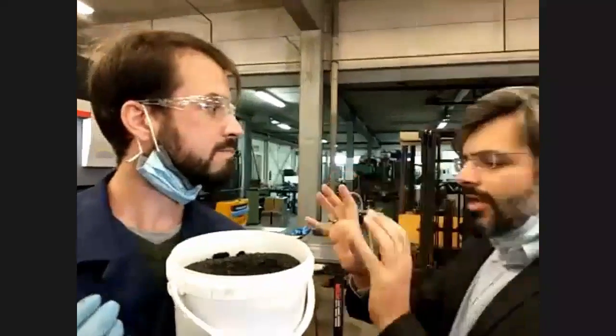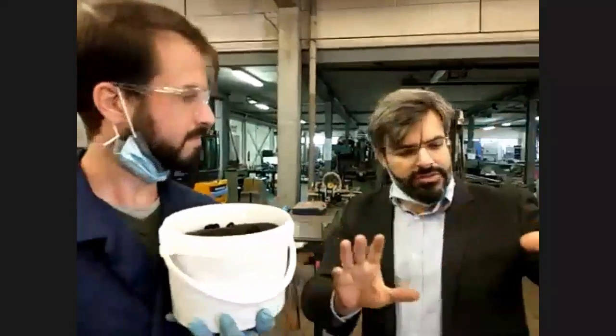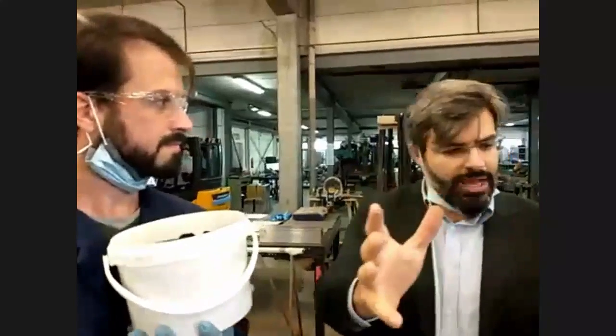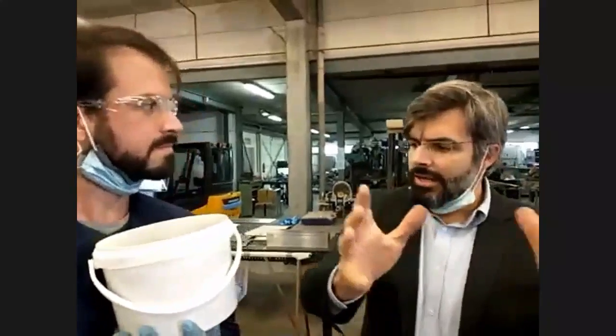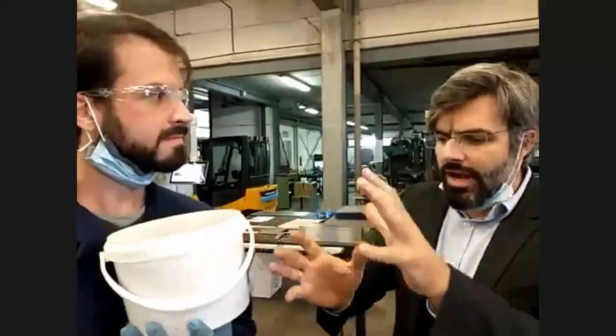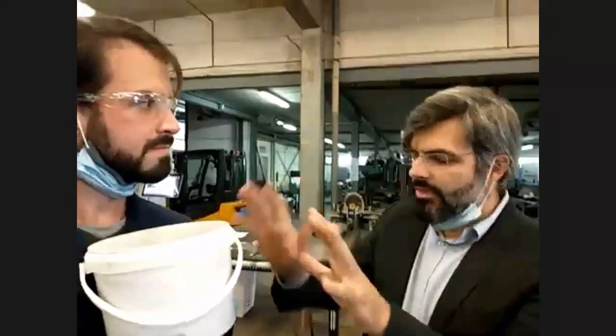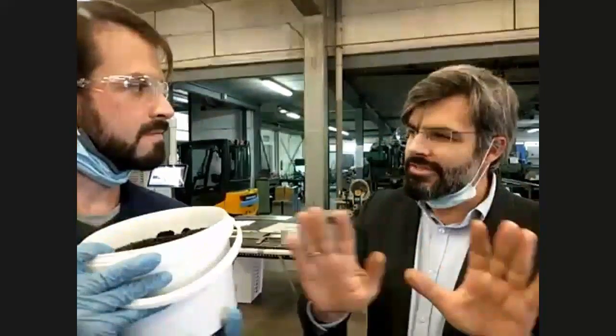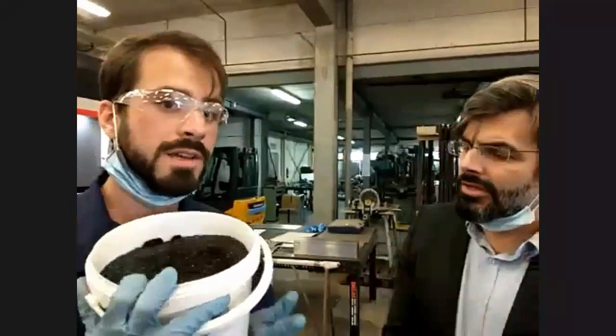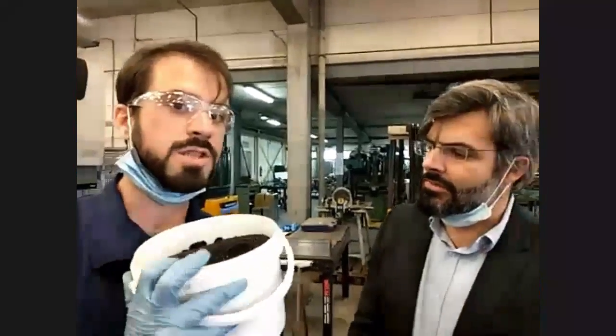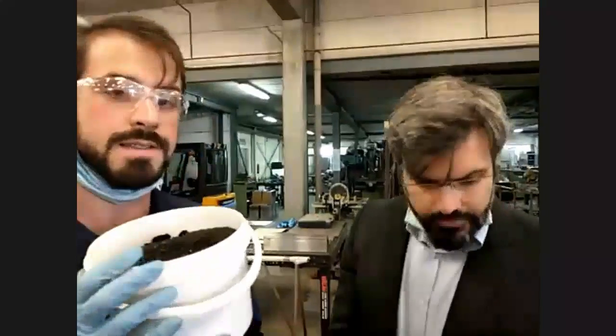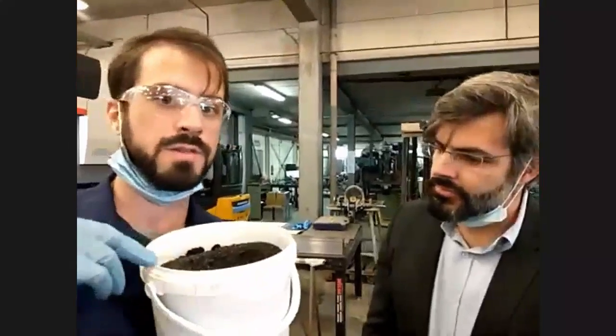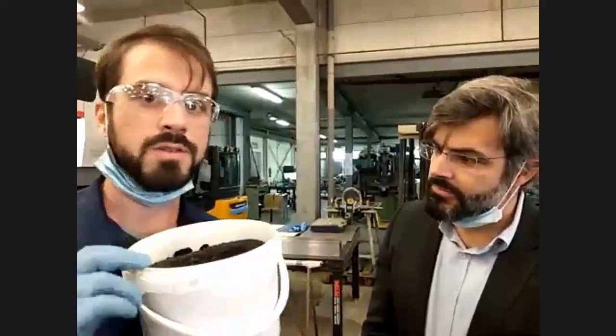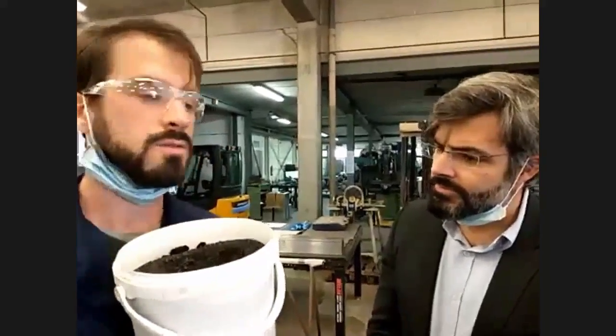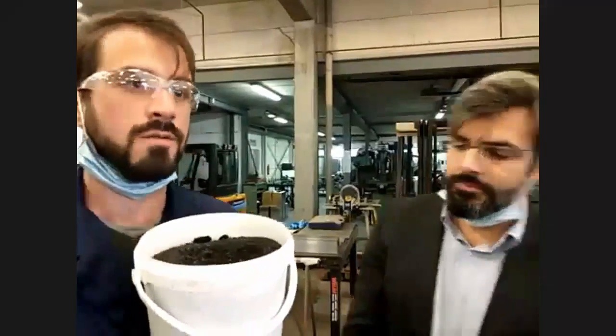Wait. Now, let me understand that right. We have this calcium aluminum silicate system. That's the classical cement, right? And now what we are doing, we're making these iron silicates, maybe with a bit of calcium. So we are creating this parallel universe. Is this the whole story? Actually, you're right. We are creating a completely different binder system, which is based on these iron silicate slags. In this case, also because we have in the bauxite residue still aluminium as well, and also calcium, an iron calcium aluminum silicate glass, which is basically a novel binder system.